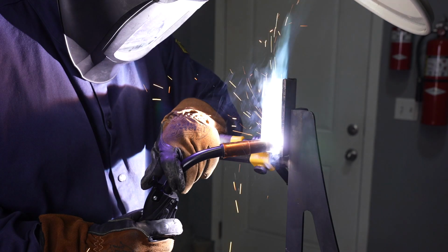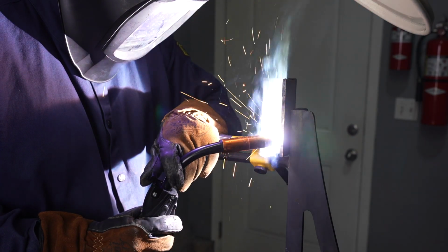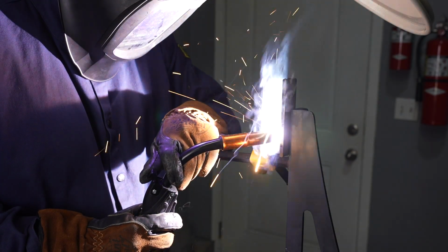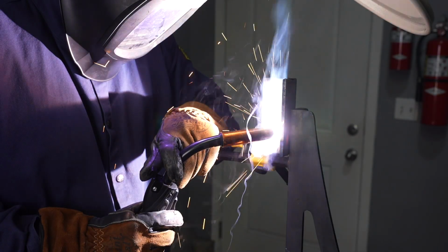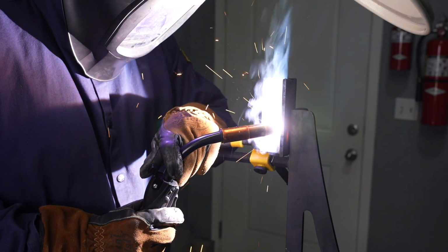So one of the biggest advantages in my mind of running gas shielded flux core compared with solid wire is that you can weld uphill with a stringer bead and have nice hot settings, just about the same that you'd have when you're running in a flat or horizontal position. So if you notice, I'm just keeping that wire up on the leading edge of the puddle. What I like to picture is a glass of water filling up, and you just keep your finger right on that surface as it fills up.